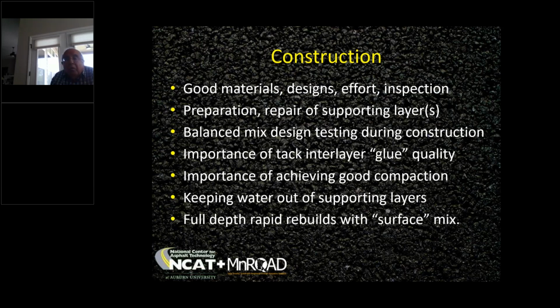And one of the ways that you can overcome the potential liability of poor performance of tack is to do a full depth rapid rebuild. And this is an exciting study that we're doing right now for South Carolina. At South Carolina DOT, they have really high traffic truck lanes that are completely failed. And they wanted to know, can we go in there and do 1,000 to 2,000 feet overnight and do a full depth rebuild, doing a really thick layer placement in a single pass? Because the book says you can't do that, but can we do it?